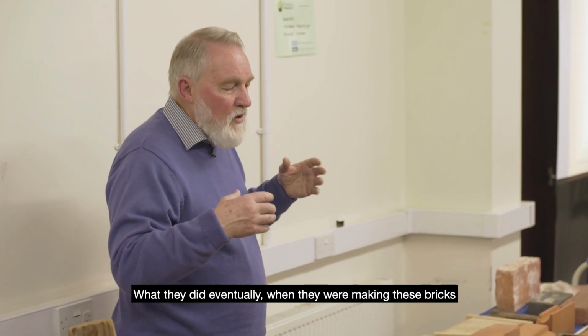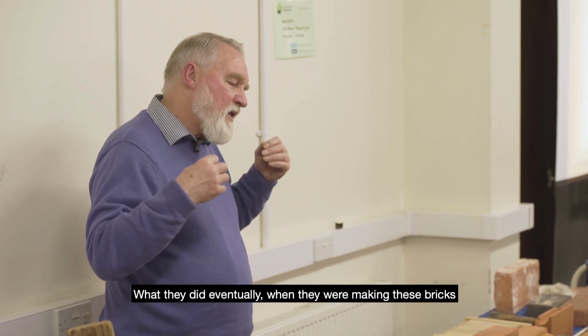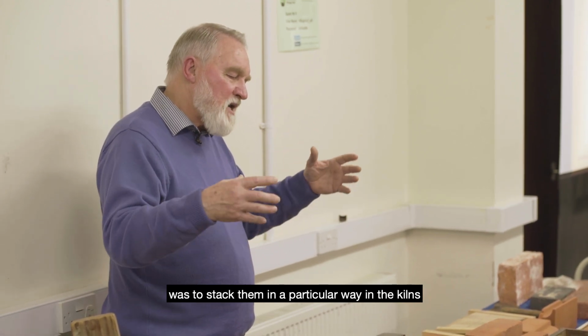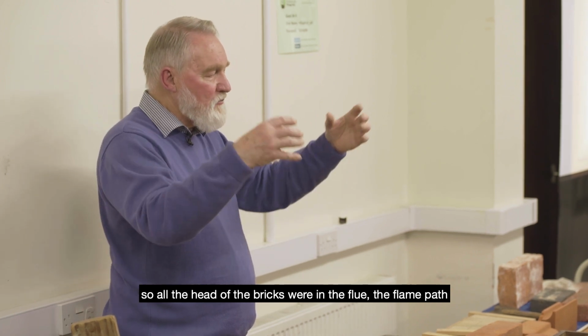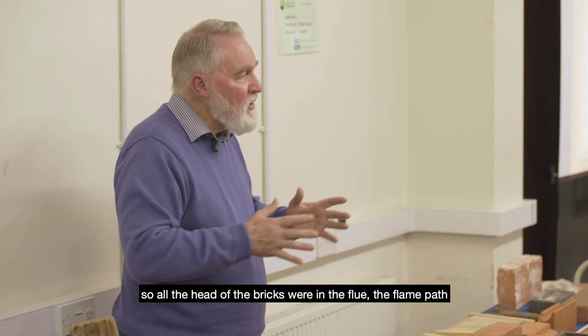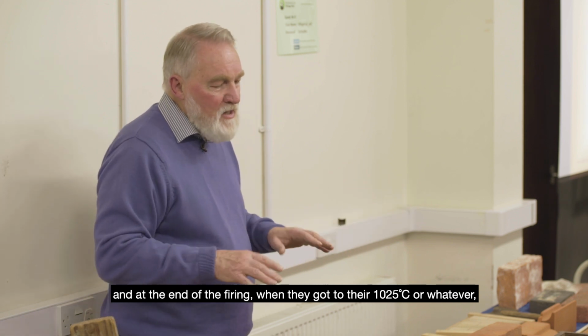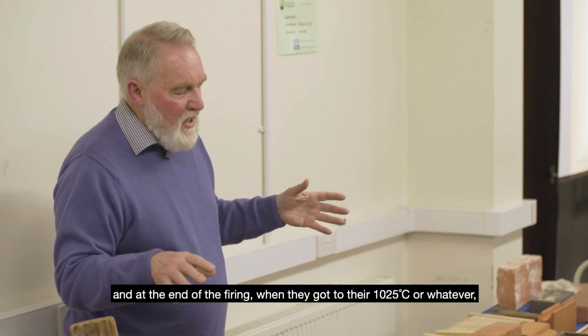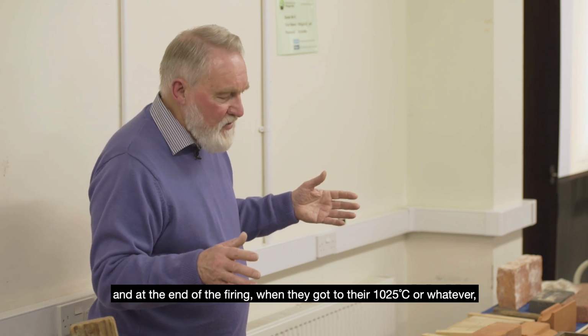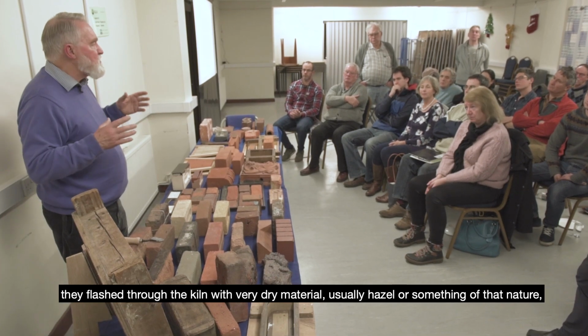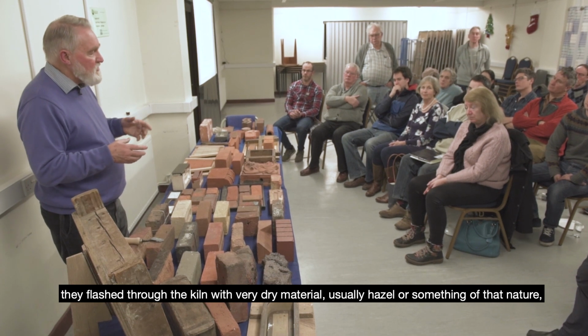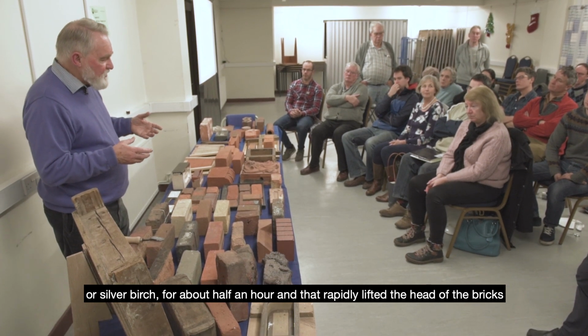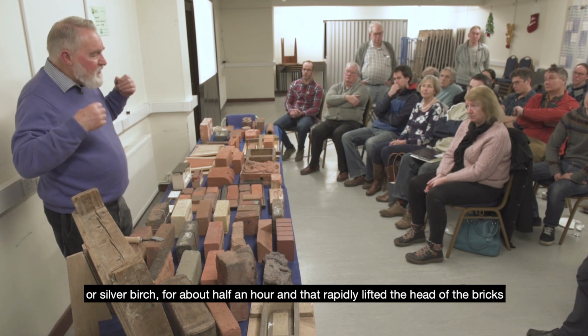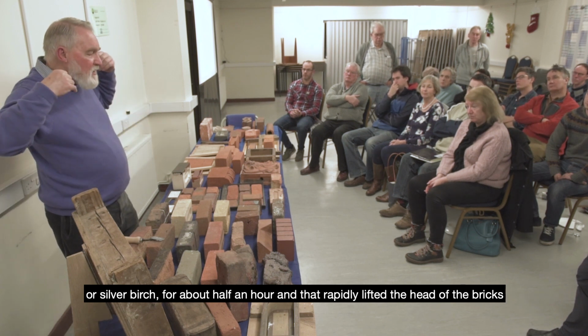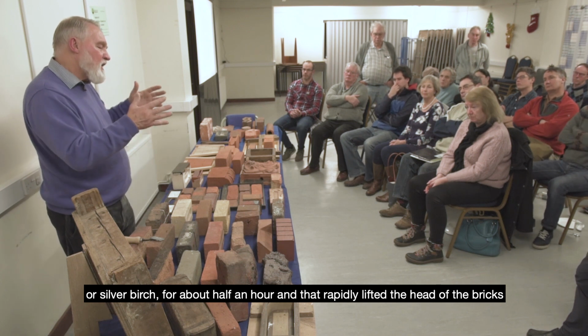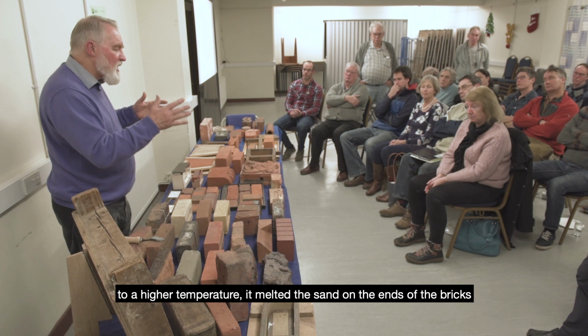And what they did eventually, when they were making these bricks, was to stack them in a particular way in the kiln, so all the heads of the bricks were in the flue, the flame path, and at the end of the firing, when they got to their 1025 degrees or whatever, they flash through the kiln with very dry material, usually hazel or something of that nature, or silver birch, for about half an hour. And that rapidly lifted the head of the bricks to a higher temperature.